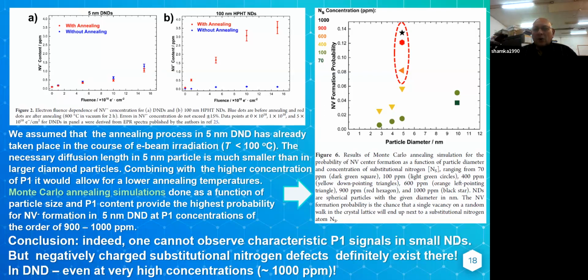The conditions of migration of vacancies in small particles are not the same as in larger particles. It means that annealing in small nanoparticles appears even at lower temperatures, below 100 centigrade. 100 centigrade, in fact, may be achieved when you irradiate the sample itself. In any case, it's self-annealing.